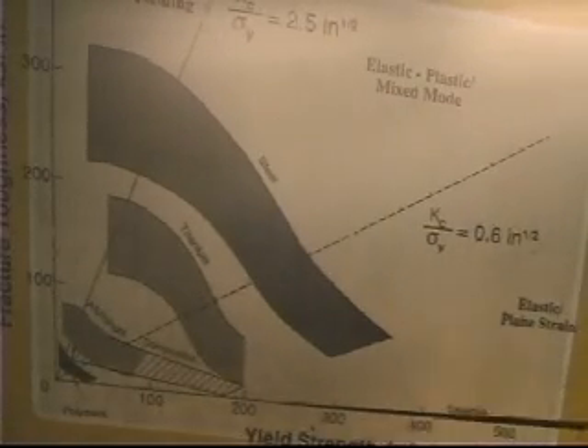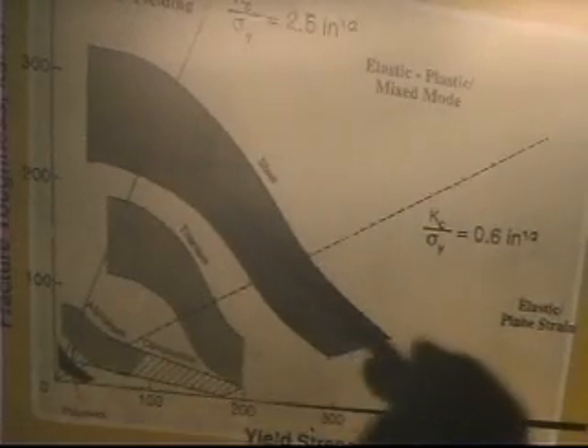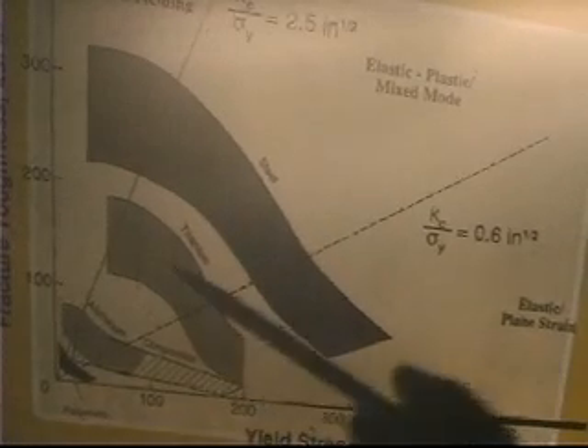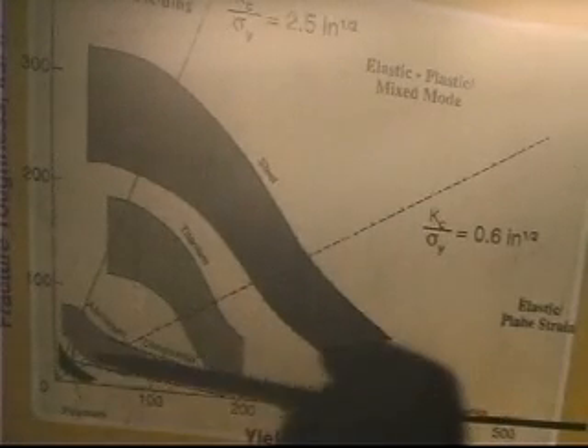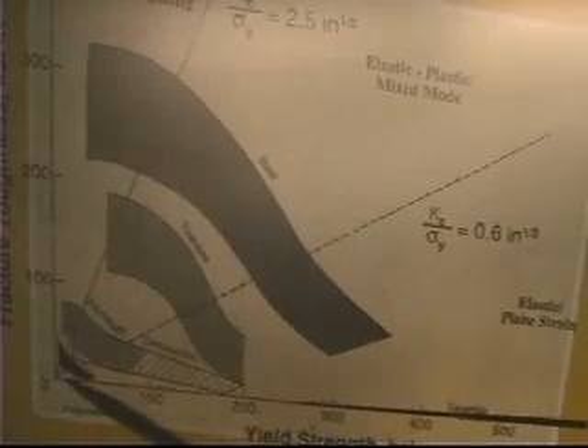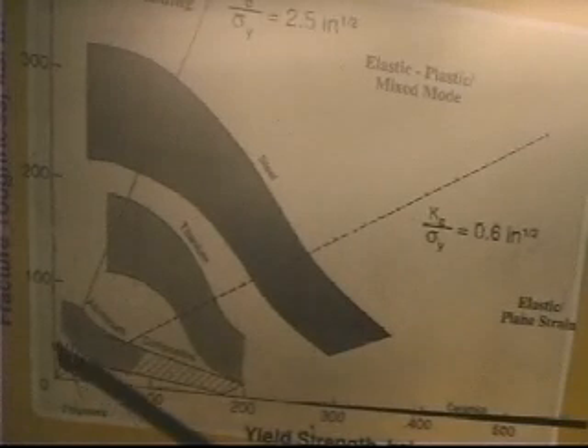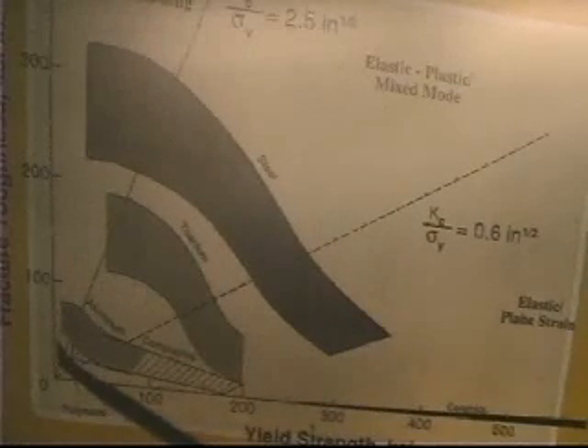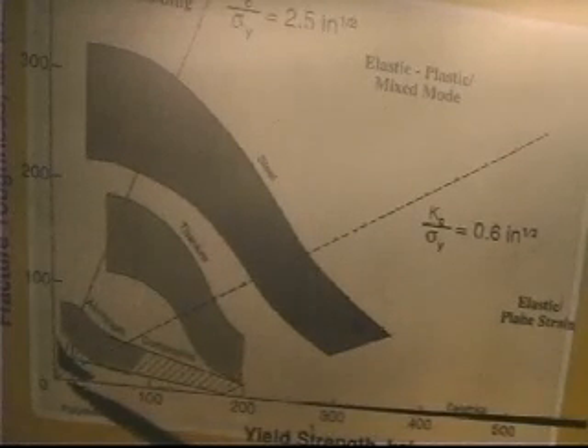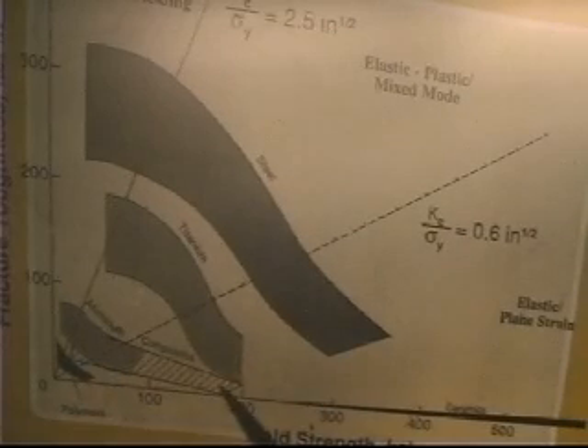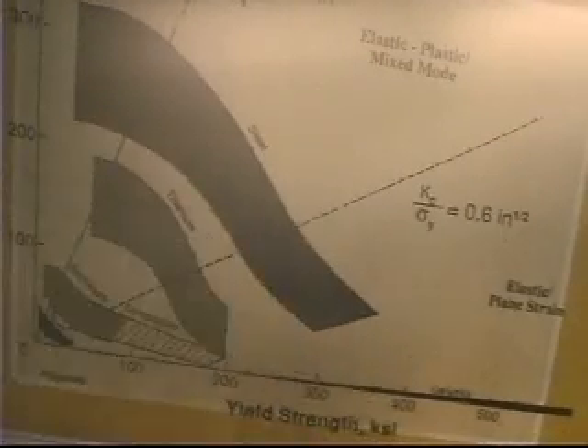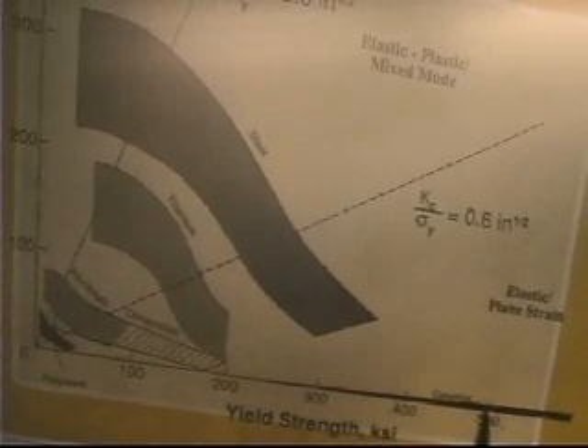Most of the structures we build in the world are here in what we call the elastic plastic range, and we use elastic plastic fracture mechanics for it. Turns out you can use steel at very high stresses. You can use titanium at lower stresses. You can use aluminum at lower stresses. You can use polymers in here. They actually cross this region, but you're getting very, very low stresses. Many of the composites end up being somewhat brittle. They're outside this middle band that you'd like to design things in. Ceramics never even saw the light of day.